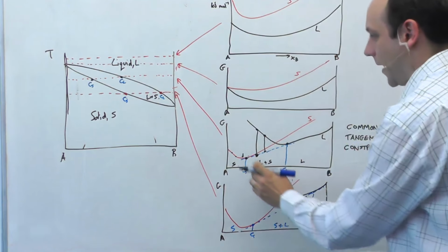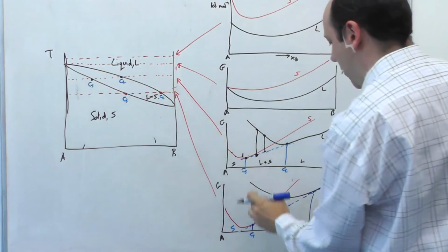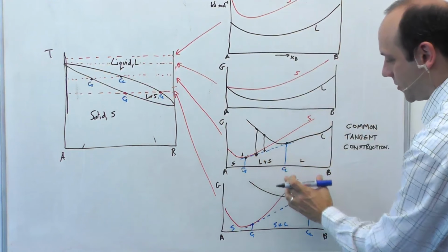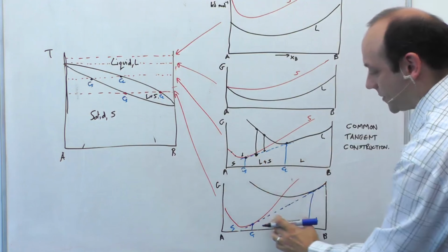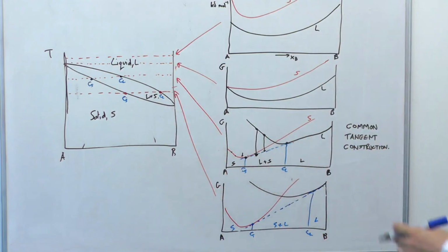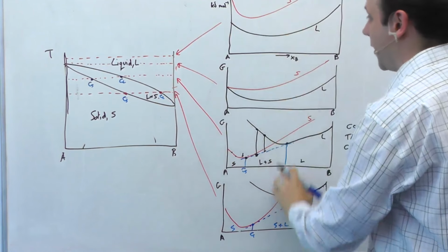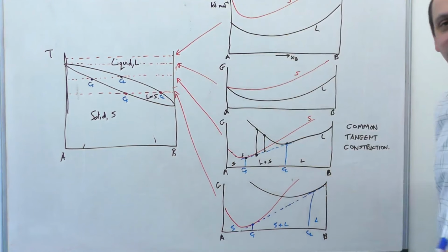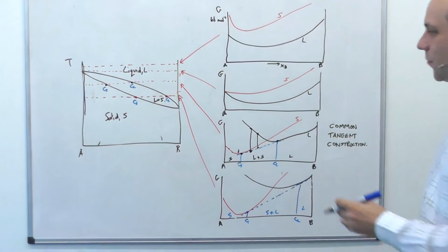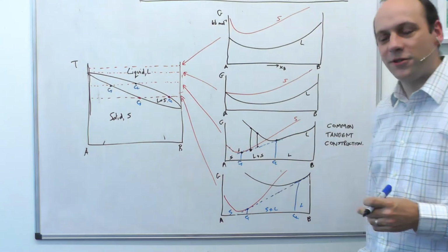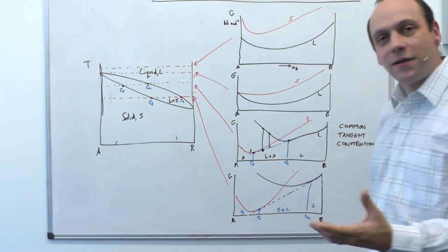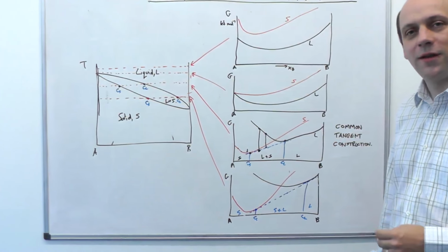liquid phase region. And as we come down in temperature, as these two have moved relative to each other and the liquid's gone further up, what's happened is this liquid plus solid region has translated over to the right. And it's just a sketch, so obviously it's not perfectly accurate. But as we've gone down in temperature, the liquid has moved gradually up relative to the solid curve. They've probably changed shape slightly. And we've constructed the phase diagram at each temperature. What we then move on to do is look at eutectic diagrams, the other type we've seen, and then we'll be done for this segment.